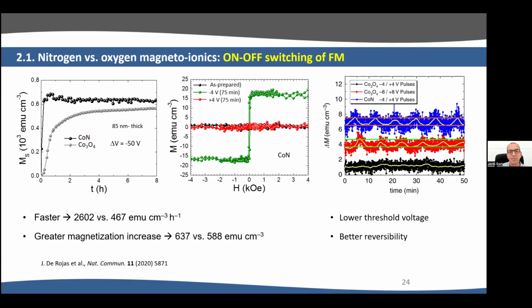And we can induce this Magneto-Ionics switch applying a relatively low voltage of -4 volt, +4 volt. So cobalt nitride actually shows good cyclability here in blue at these voltages of 4 volt. However, for cobalt oxide at 4 volt, there is no cyclability, and we need to apply 8 volts in order to see this cyclability.